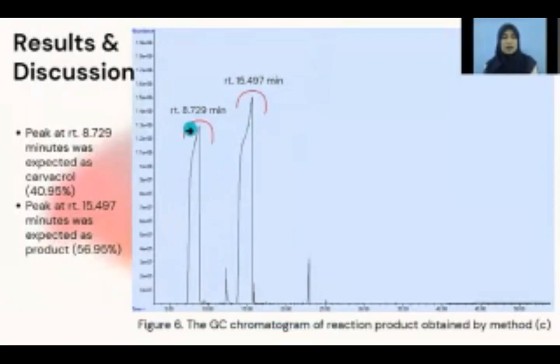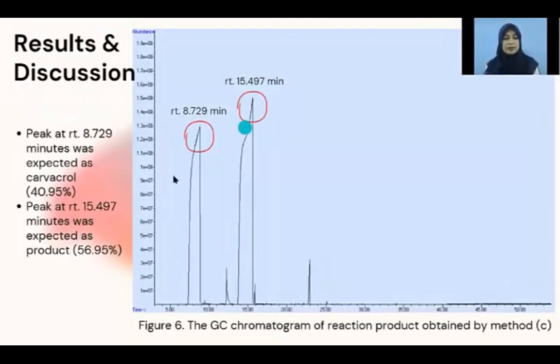Figure 6 shows the GC chromatogram of the reaction product obtained by method C. We also can see that there are two main peaks. The peak at the retention time of 8.729 is expected to be carvacrol, and the peak at the retention time of 15.497 minutes is expected to be carvacryl ester.